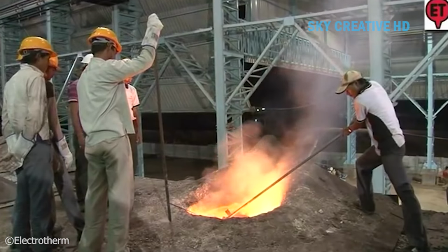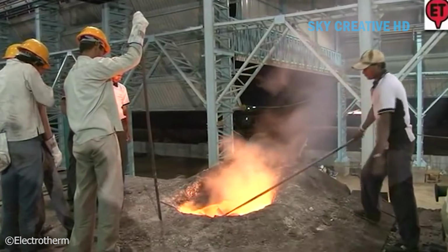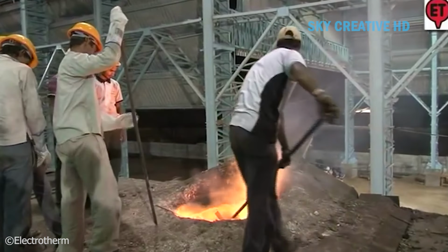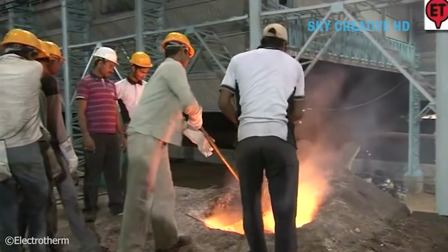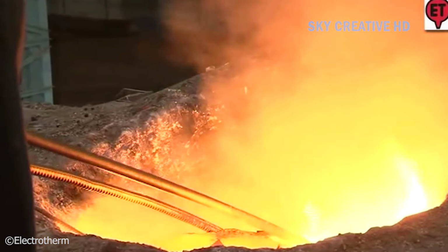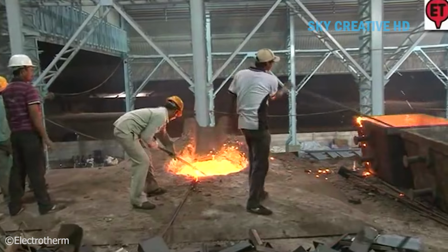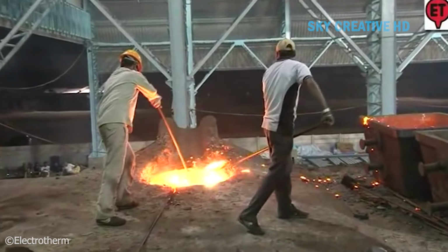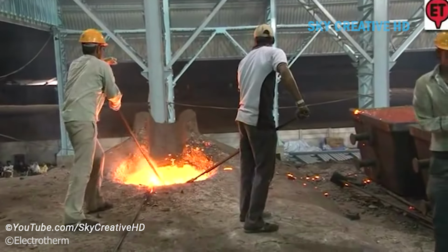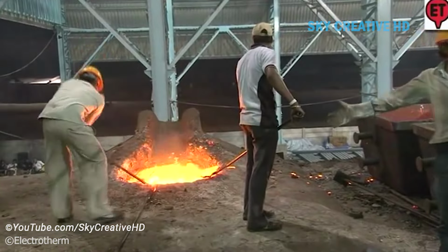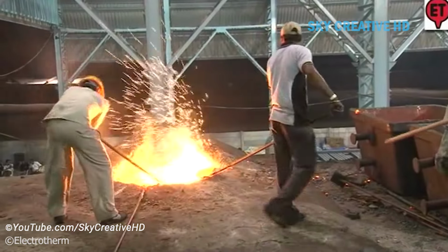But here's what makes this special. The ladle isn't just a bucket. It's equipped with argon purging systems that bubble inert gas through the molten steel, removing dissolved gases and floating out non-metallic inclusions that would compromise the final product's quality. This refining process, called ladle metallurgy, can take 20 to 40 minutes, but makes all the difference in producing clean, high-quality steel.